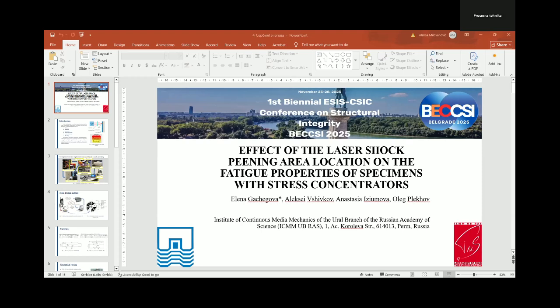They demonstrated improved fatigue life after laser shock peening. Crack initiation was delayed, and crack growth rates were reduced compared with untreated conditions. And fatigue tests showed us similar results. We see that fatigue life increased up to 85% after laser shock peening.